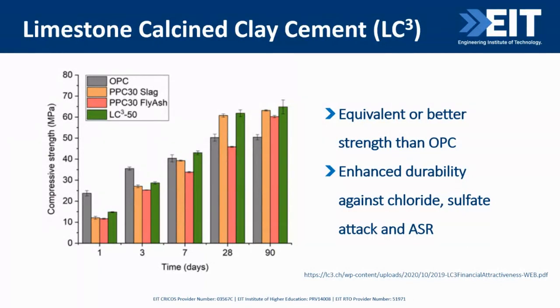Reasons for this improved performance are the additional chemical reactions compared to ordinary Portland cement, including the pozzolanic reactions of calcined clay and limestone reactions, and most importantly, the synergetic reaction of the calcined clay and the limestone. Because the alumina contents of calcined clay enhances the limestone reactions.